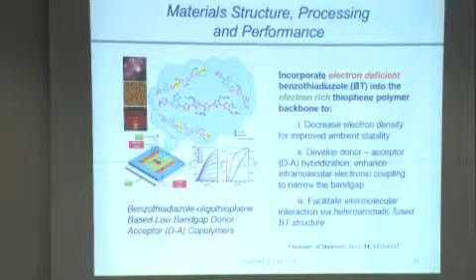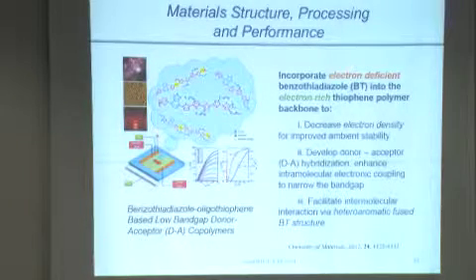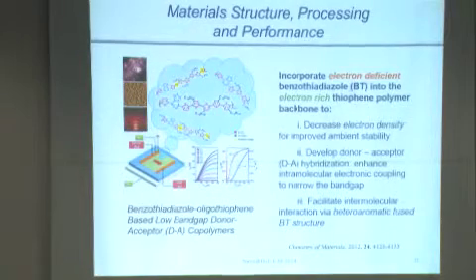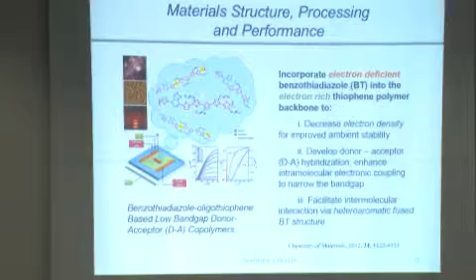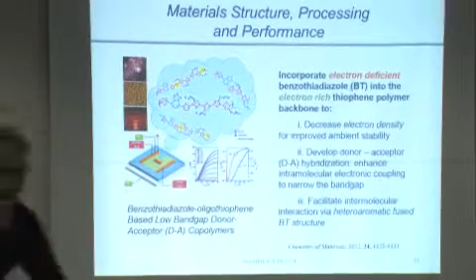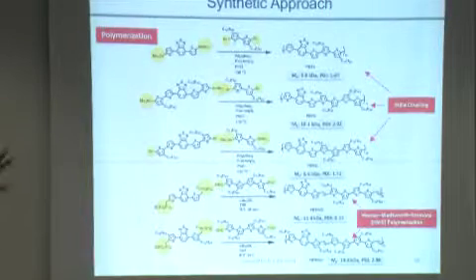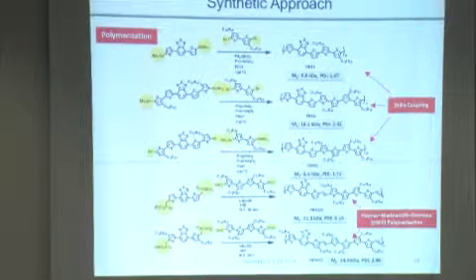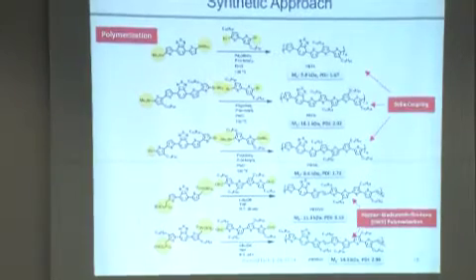Right, so the particular project that I'm going to highlight here is incorporating electron-deficient benzothiadiazole into an electron-rich thiophene polymer that leads to improved ambient stability. There's more intramolecular coupling that can narrow the band gap, and we may be able to facilitate intermolecular interactions because of this fused heteroaromatic unit. I'm not going to dwell on this, but this is the synthetic approach that Boy-Fu used to ultimately prepare the polymers.